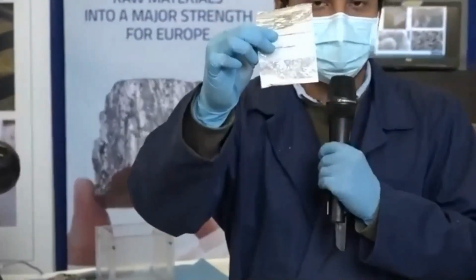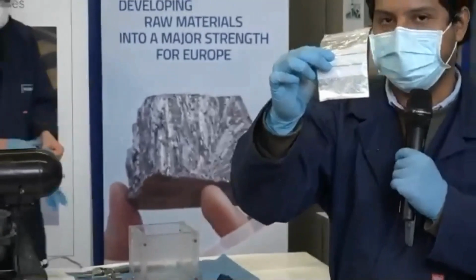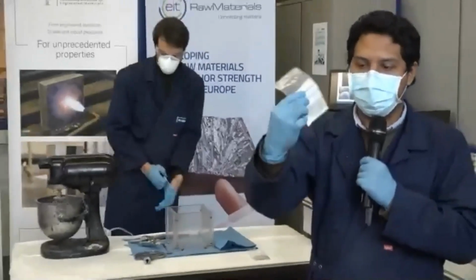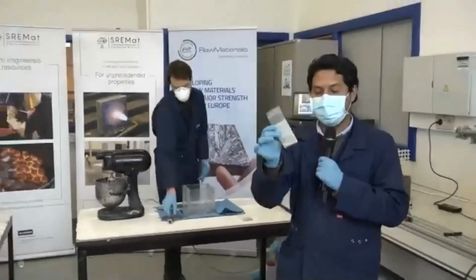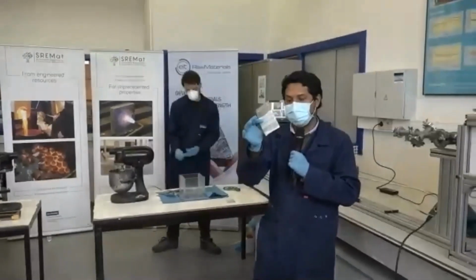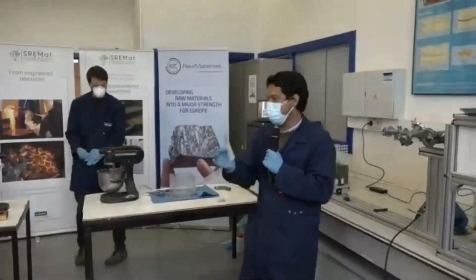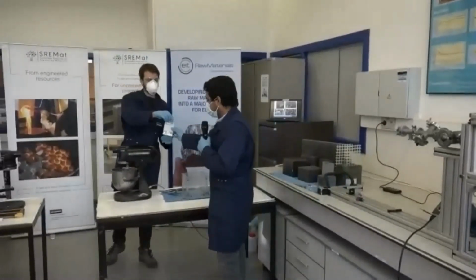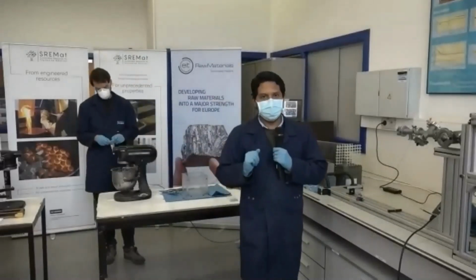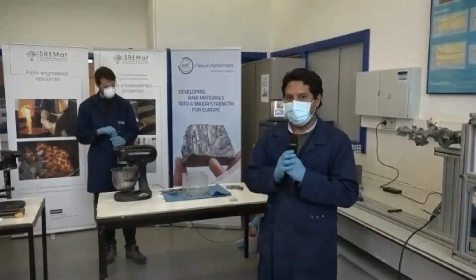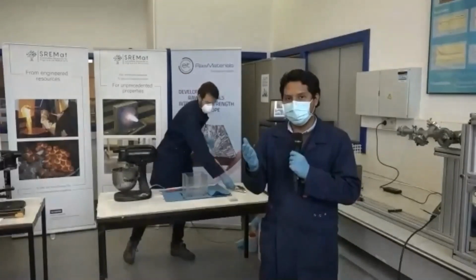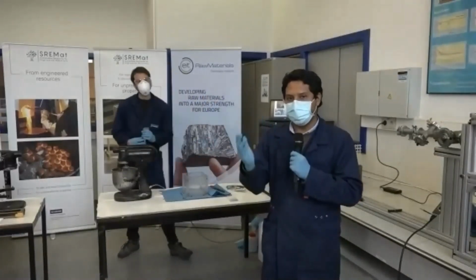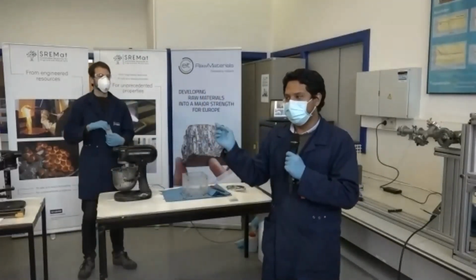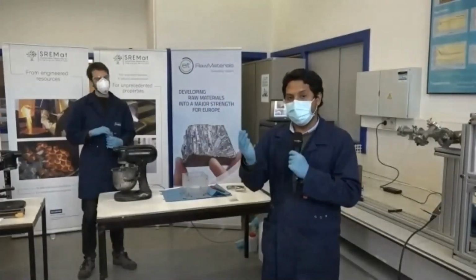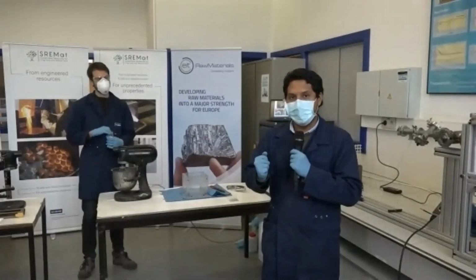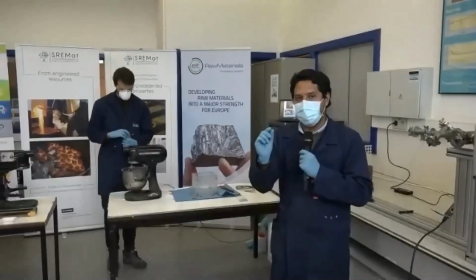As in the case of the hybrid systems that the guys explained to you before, we make small additions of this type of components. This is called a surfactant and has a specific reason to be in the mix design. Now, Tobias will add that to the mix design. While you are mixing, I was telling you that we introduced quite a lot of air into the mixture. That surfactant will allow us to keep that air inside of the paste and to create small bubbles.